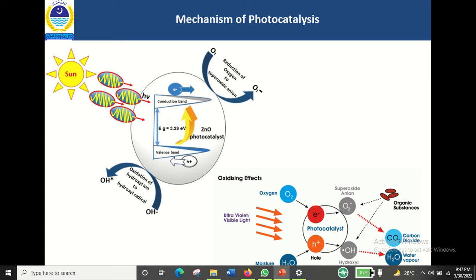Among them, zinc oxide is a semiconductor photocatalyst with a high oxidative potential, excellent photosensitivity, moderate stability, and variable band structure, which has sparked widespread interest in photocatalytic fuel production and environmental remediation. The zinc oxide has a band gap energy of 3.29 electron volt. When sunlight interacts with the zinc oxide, it excites the electron from the valence band to the conduction band, and these electron-hole pairs drive the photocatalytic activity of the zinc oxide.